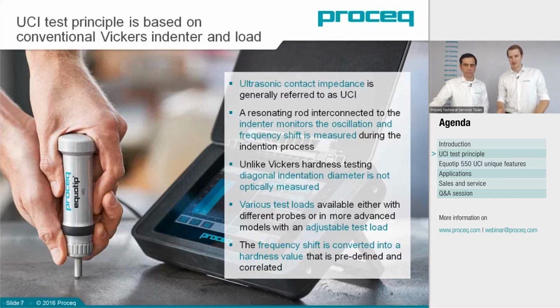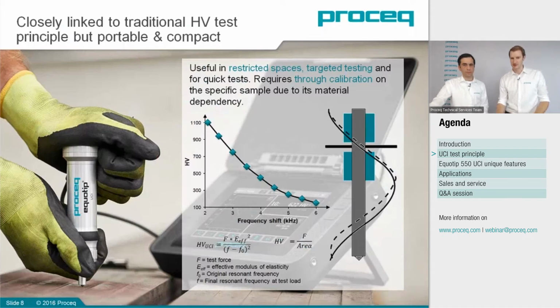Once the frequency shift is measured, it has to be converted into a hardness. This can be done with a conversion curve. You can see this here on the chart in the middle of the slide. That's an example of such a conversion curve. Something very important to mention here is that this curve is actually only valid for steel, unalloyed steel, or low alloyed steel. What happens if you have other materials then? If you have other materials with another elastic modulus, you need to adjust this curve.